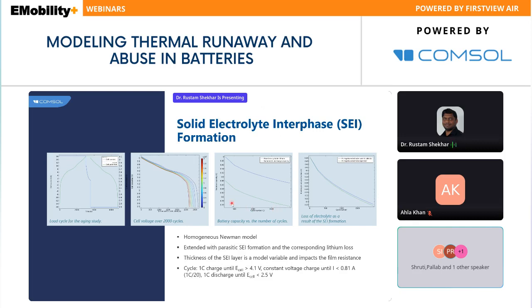So with cycle number, how am I losing my capacity? From the first cycle to the last cycle, how the capacity is varying, and the spatial variation also. So at what location am I losing more capacity? As we can see, which is expected, at the solid electrolyte interphase (SEI) we are losing more material. That means the reaction is more, and then we are losing more material.